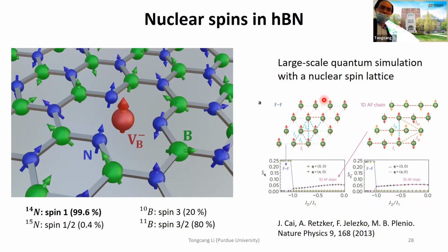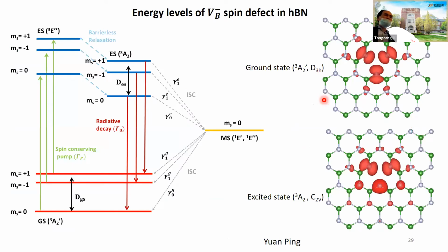So if you want to control nuclear spin, first of course, the energy level is quite complex, and you need to understand them. This is a calculation done by our collaborator, Professor Yuan Ping. The ground state has spin 1 with zero field splitting of about 3.5 gigahertz. The excited state first goes to the 3E double prime state and then through a very fast relaxation goes to the 3A2 excited state. Again, this field is very new, so people don't know the parameters. Before our work, people didn't know what this D is, and the other parameters.